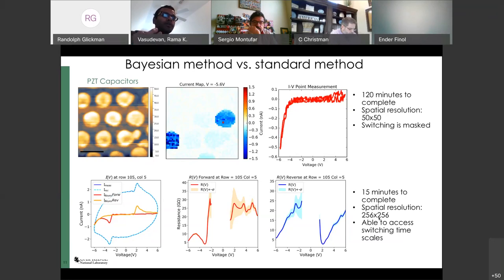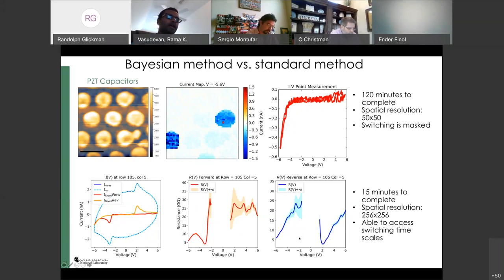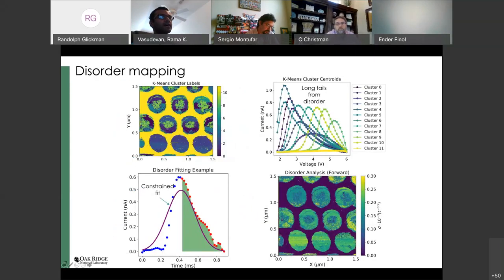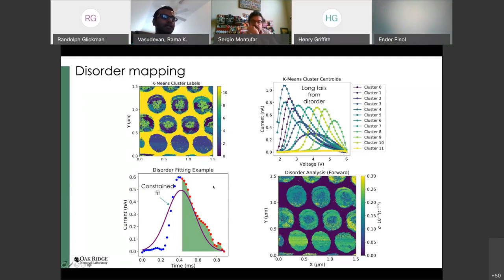The only downside is performing Bayesian inference on every curve, but because it's a Bayesian model we still maintain uncertainties in our reconstructions. We can also extract more physics — for instance, long tails in the displacement currents indicate more disorder in the switching process. By applying a standard Bayesian inference technique, we accelerate our imaging by a factor of 10 to 100 times with no loss of resolution — in fact, with gains in both temporal and spatial resolution.